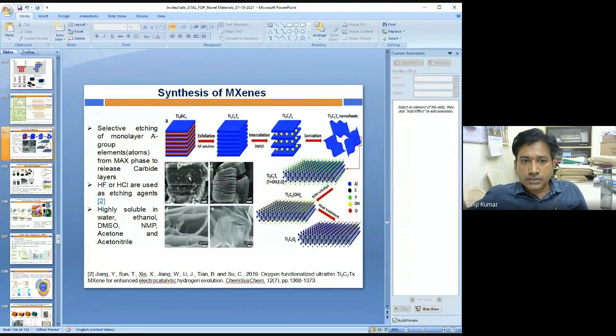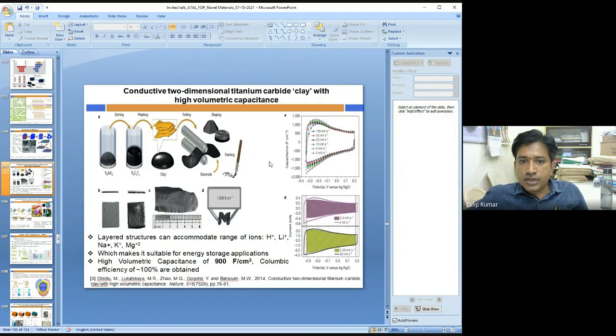So the synthesis part. We definitely go for HF etching or HCl etching, though predominantly we go for HF etching only. These are highly soluble in water, ethanol, dimethyl sulfoxide (DMSO), acetone or acetonitrile. And I can show you the applications. Yeah, you can look at these applications.